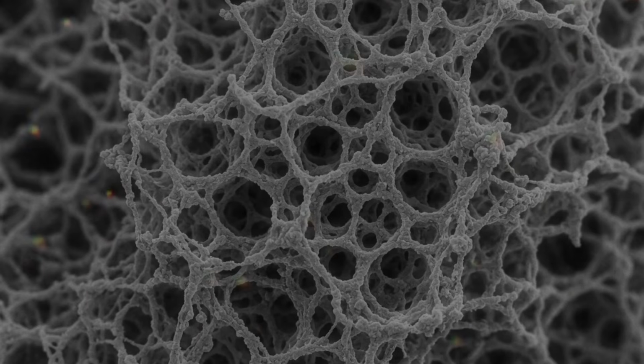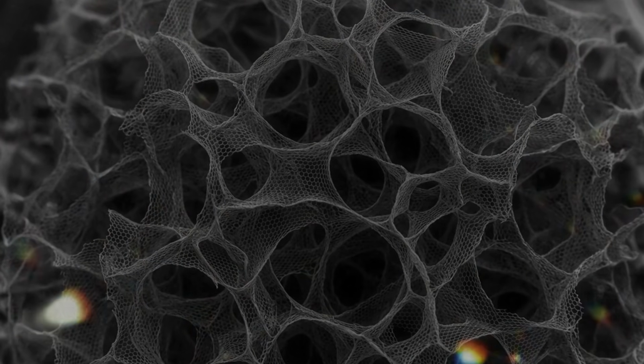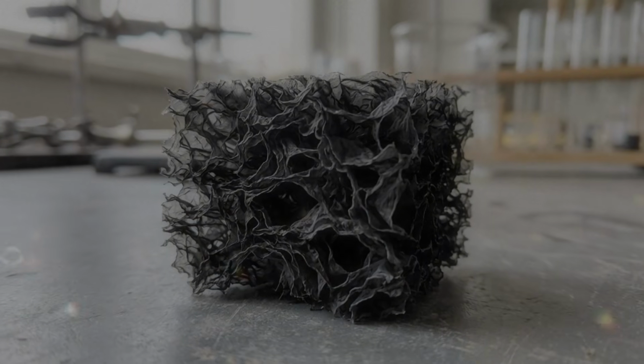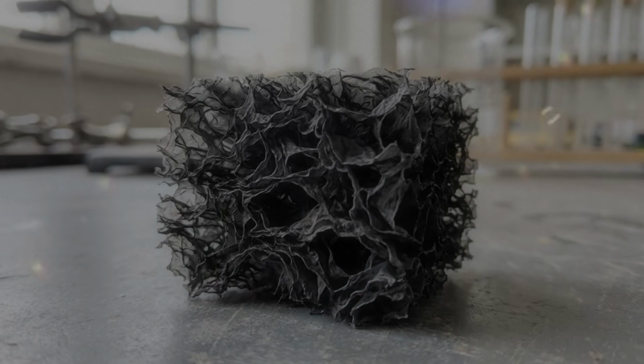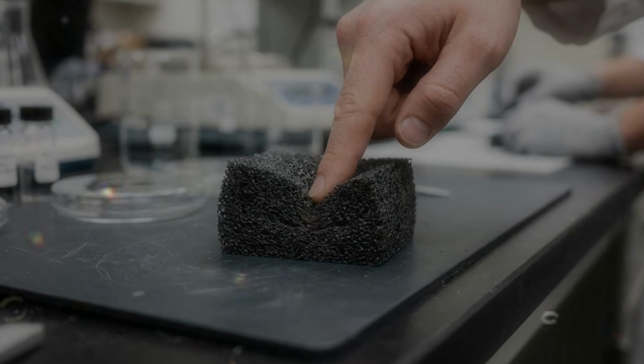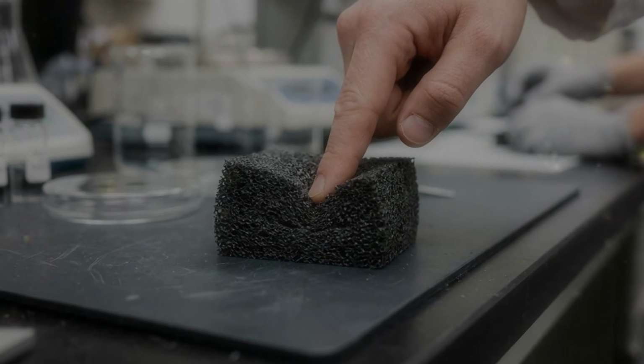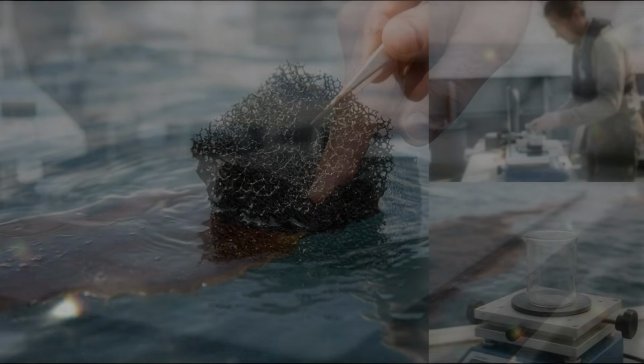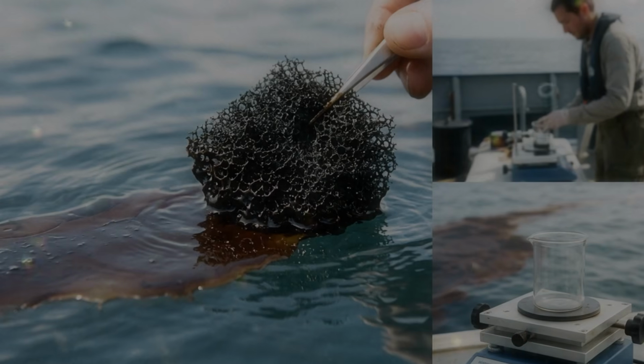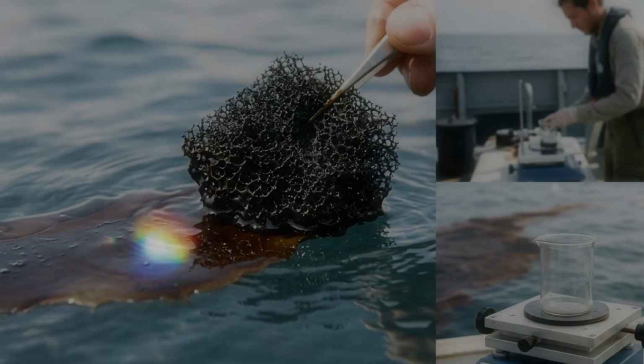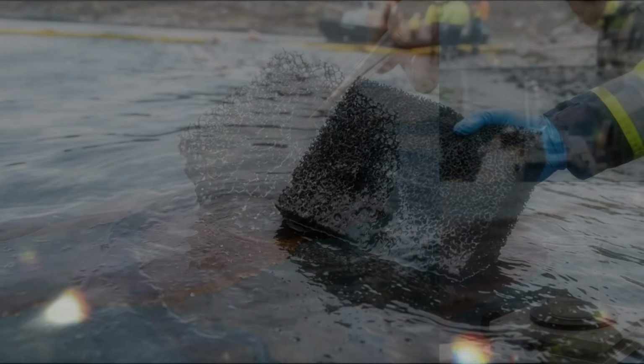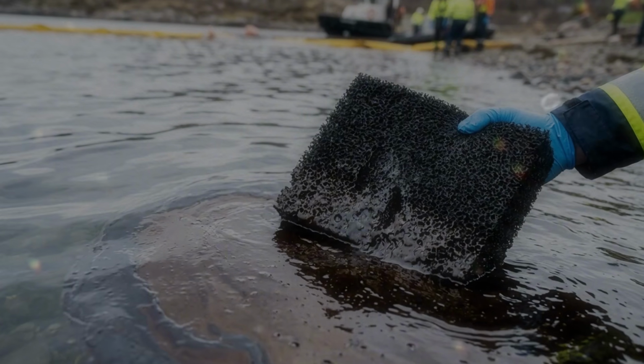Carbon-based aerogels behave differently. A single high-quality graphene sheet can conduct heat very well along its surface. The carbon bonds provide an efficient route for energy. Inside aerographene, however, the sheets are folded, separated, and connected imperfectly. Heat moving through the sample cannot travel along one continuous sheet from beginning to end. It must cross wrinkles, edges, contacts, and gaps. Each transition slows the transfer. The overall material can therefore conduct heat much less effectively than an isolated sheet of graphene.